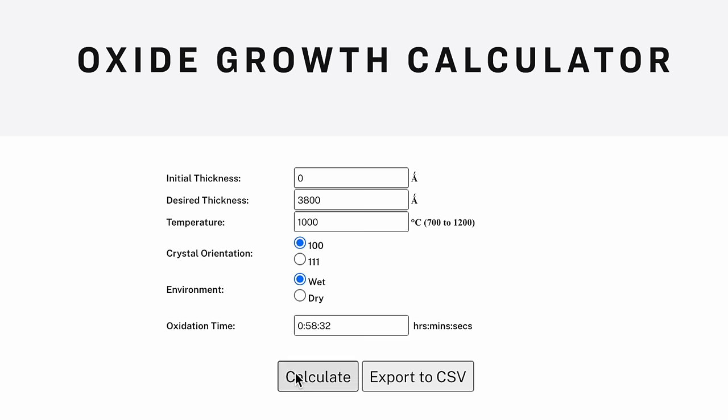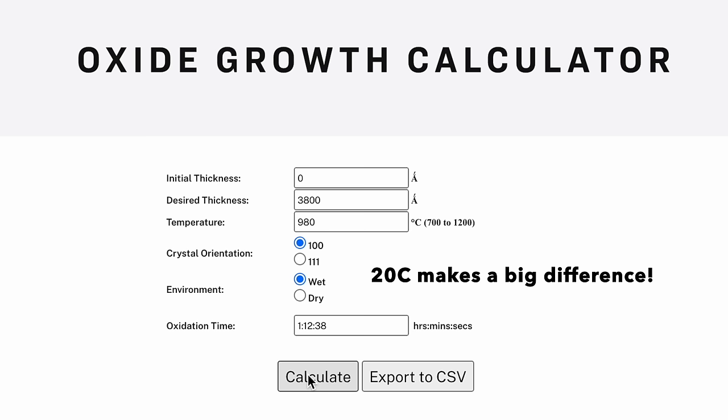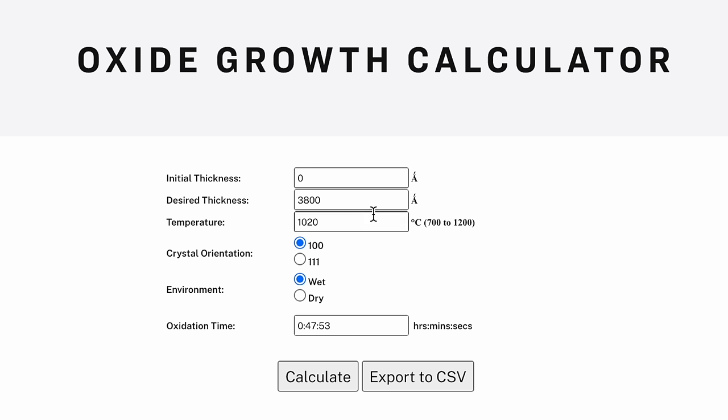There's only one real caveat here. The growth rate is pretty sensitive to the temperature of the furnace, as well as the amount of moisture in the air. It's possible that even if you run these numbers in real life, you'll be off by a fair amount. The best approach to getting the oxide thickness correct is to use the formula, and then verify the results of the chart. That should maximize the chances of success.